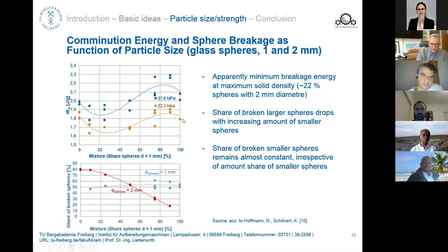Yeah, so this is another point, another investigation also accompanied by Schöner, where again glass spheres were investigated, mixtures of glass spheres of different sizes, and here already you can see an influence of the percentage of glass spheres, indicated here as 1 millimeter glass spheres. Let's say you start at the beginning at 10% of the glass spheres and different pressures. With 10% of the finer glass spheres, the specific energy consumption is reducing. But then the higher your percentage of the finer glass spheres is getting, the more the influence of the larger strength of these finer particles is seen here.